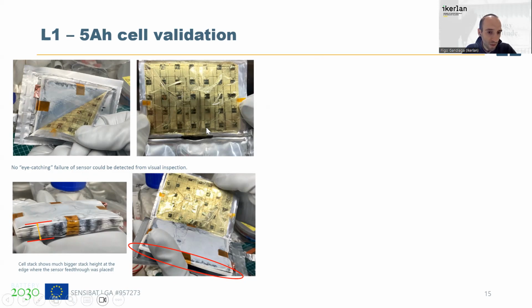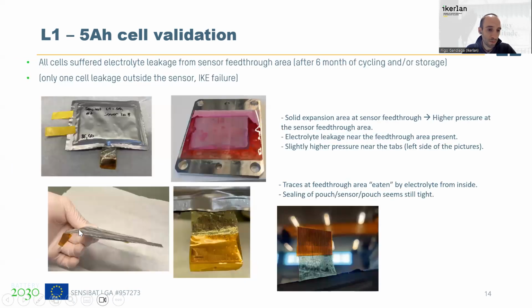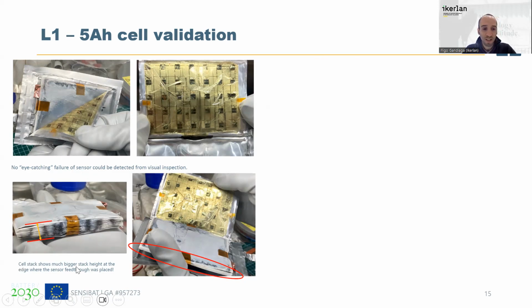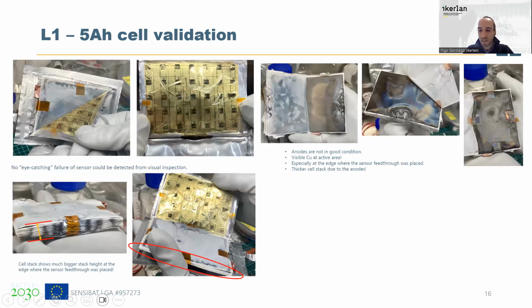Another thing that we saw is that, as we saw in the previous picture, the cell stack shows much bigger stack height at the edge where the sensor feed-through was placed. So here we can see that it's widened, and we started to also analyze the electrodes of the cell, and we saw that the anodes were in not good condition. We can see some copper at the active area, especially at the edges where the sensor feed-through was placed.